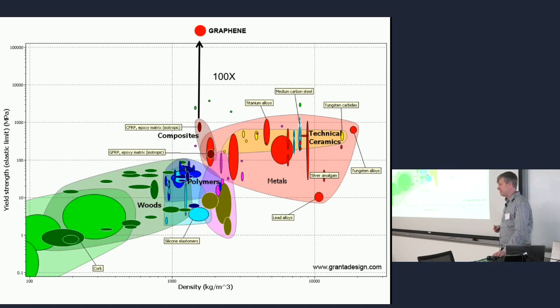I think you can see similar results, not quite as high, in carbon nanotubes, and things like very ultra small gold wires also show fracture strength much higher than the bulk, as well as small diamond whiskers and glass fibers, things like that. So we tried to think about an analogy for how strong this material is. The one we came up with is, if you imagine that this experiment is like putting a saran wrap over a coffee cup and then trying to poke through it with a pencil.